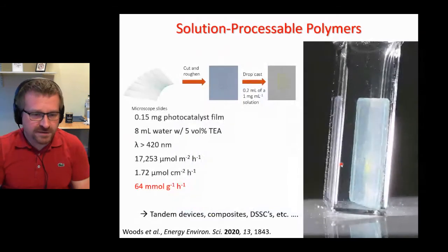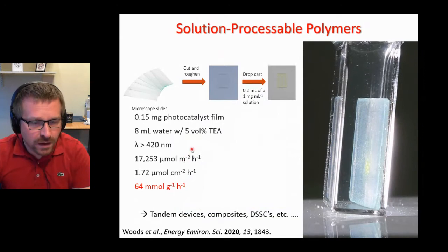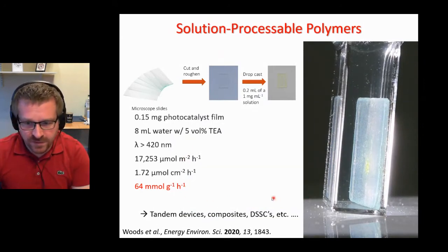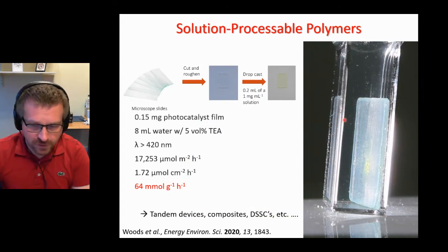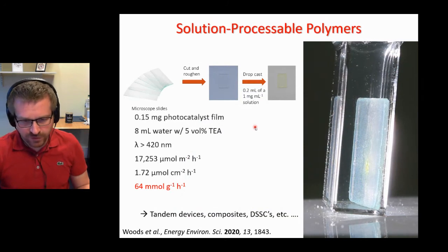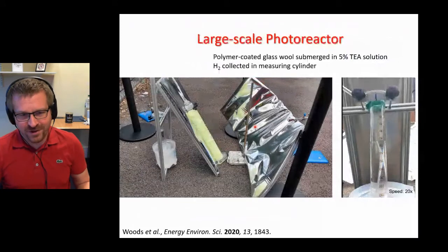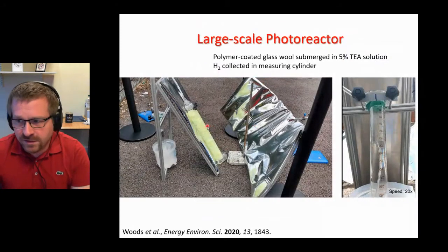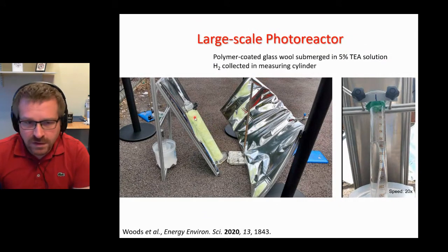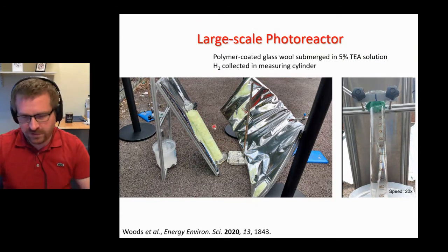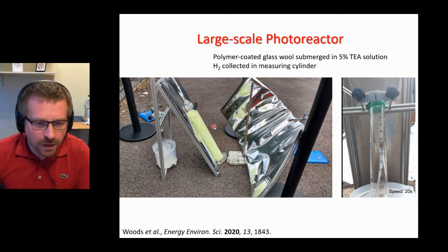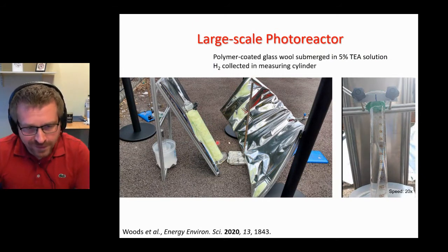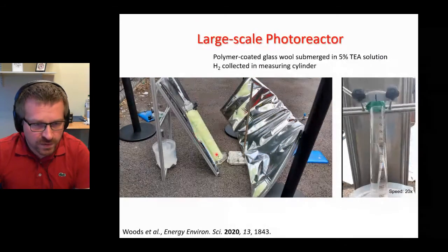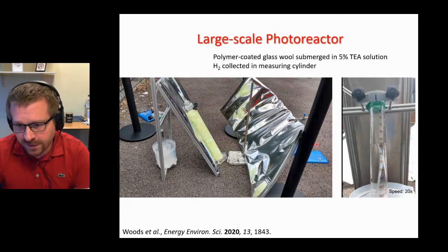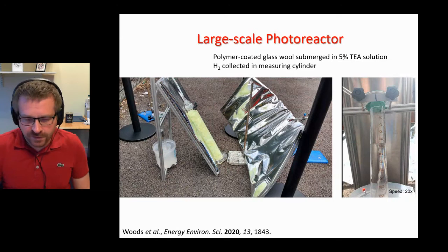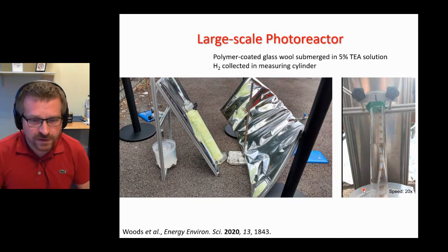We explored this quite extensively, and I'll skip ahead for a few years here, to materials that are much more active in the end. And you can see even here on the solar radiation coming, hydrogen gas coming off the surface of the material. And this is quite important in terms of scale up, because that's really the key challenge. To explore this a bit, we looked at scaling up a reactor by covering glass wool with this catalyst and just leaving it out in solar irradiation in the UK, of course, so not being particularly sunny. But then over time, as light hits our photocatalyst, we start to see more and more gas being produced, and then it goes off this tube here into the cylinder. You can see over time gas being collected in the cylinder, and we can now produce significant amounts of hydrogen over time.